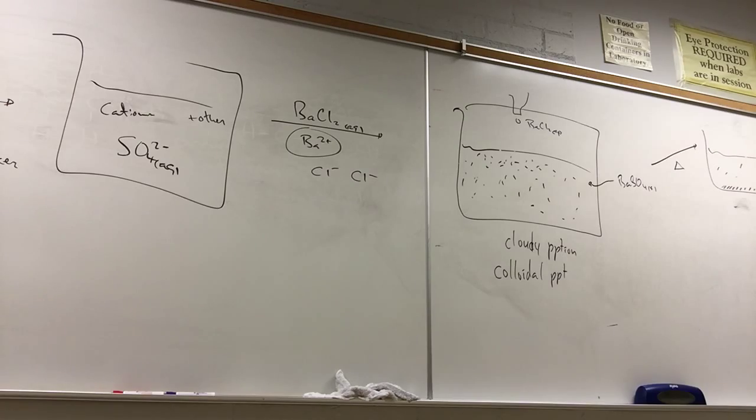Another way is to do this coagulation process. This coagulation process has a different name, digestion, when we're heating it on the hot plate. When we're heating it on the hot plate, we're trying to digest the smaller crystals, make them bigger. And so what we want to do is maximize the digestion. In other words, we want to just gently boil this for as long as possible, because the longer we boil this, the bigger the crystal conglomerates will grow, and the easier our filtration will be.